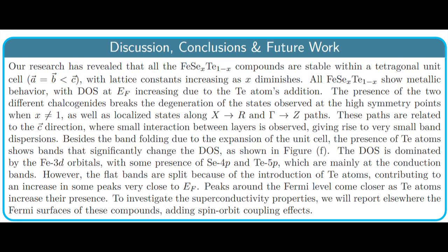Finally, the conclusions of our work. Our research has revealed that all FeSe_xTe_(1-x) compounds are stable within a tetragonal unit cell, with A equal to B less than C, with lattice constants increasing as X diminishes. All FeSe_xTe_(1-x) compounds show metallic behavior, with density of states at the Fermi level increasing due to the tellurium atom additions.